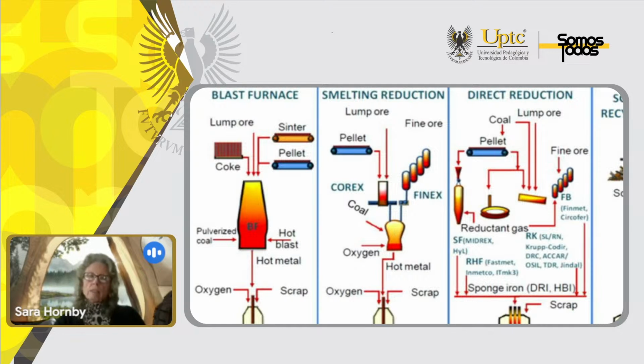The current steelmaking and iron making processes are shown here. I'm not going to go through them all. The main point to look at is the bottom line here, where we have blast furnaces producing 2.2 tons of CO2 per ton of steel making. The smelt reduction reduces to a max of 1.68, direct reduction at 0.95, and of course, scrap recycling at 100% is only 0.38 tons.